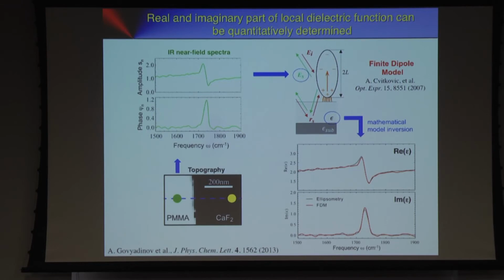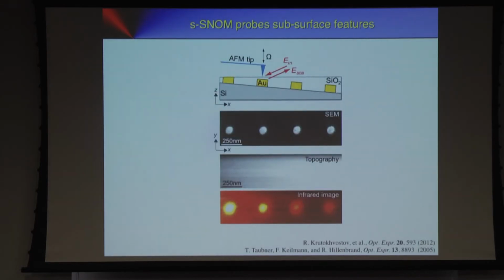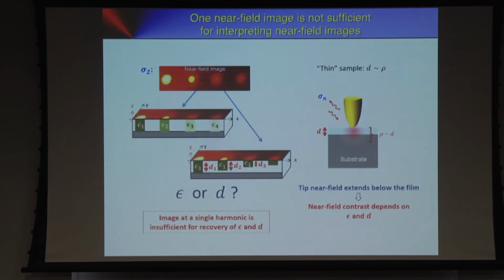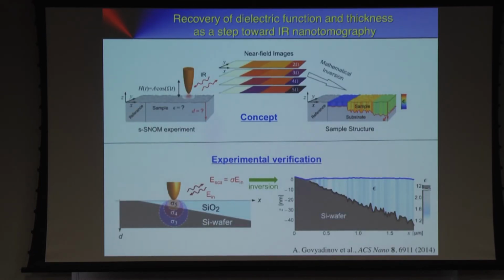So this is ellipsometry. And then the other thing is, we look into depths. Here we look at gold particles that go into depths, and we can see that even if they are deep, we see them, but they get blurred and they slowly vanish. But we look into depths. And that was the reason why we came up with the idea of doing nanotomography based on a reconstruction. And the idea is here.